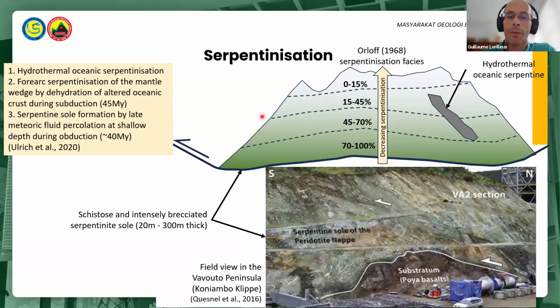Serpentinization is also an important factor, and the degree of serpentinization of the protolith appears sometimes correlated with the nickel enrichments. In New Caledonia, the serpentinization intensity decreases from the sole of the peridotite nappe upwards. This serpentinization is related to fore-arc serpentinization of the mantle wedge by dehydration of altered oceanic crust during subduction, as well as serpentine formation by late meteoric fluid percolation at shallow depths during obduction. It is later than hydrothermal oceanic serpentinization.